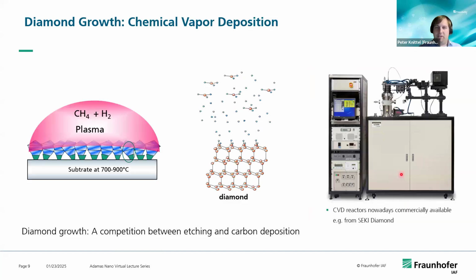Right. But how do we grow diamond? If we grow it via CVD, we ignite a plasma. All of the systems are more or less similarly constructed. So we have some kind of power source, which is in most cases a microwave, that is coupled to a resonator, where we excite a plasma. Inside this plasma, we have the constituents that we need, mainly carbon, obviously, but in addition, a lot of hydrogen, forming radicals in the plasma. From the CH radicals in the plasma, we can then build up diamond.